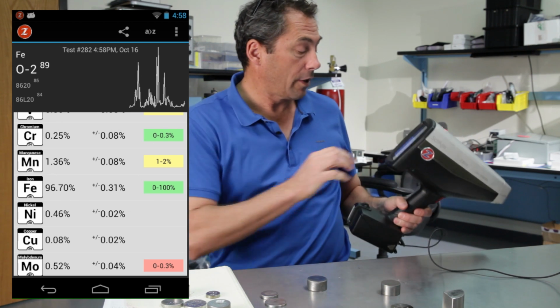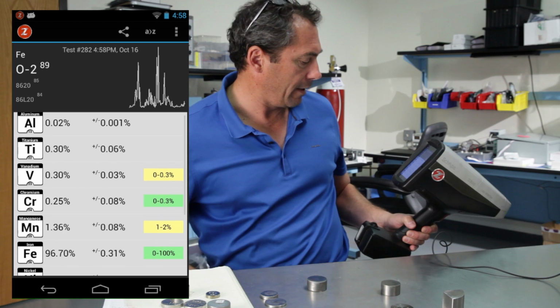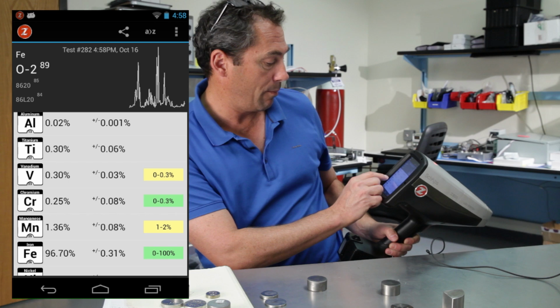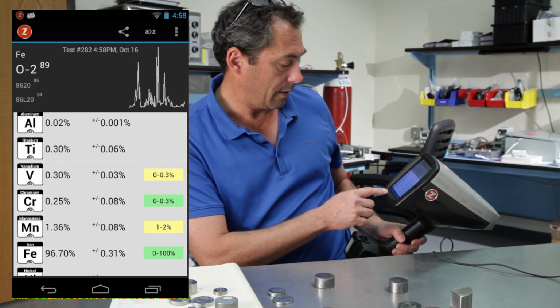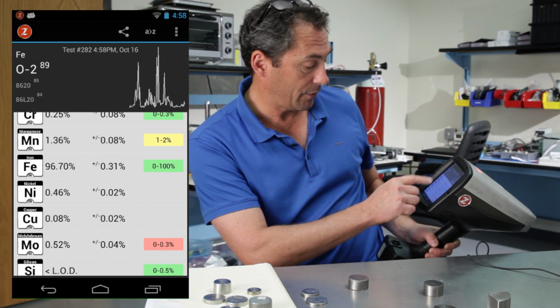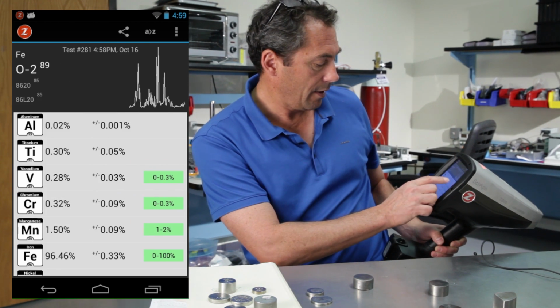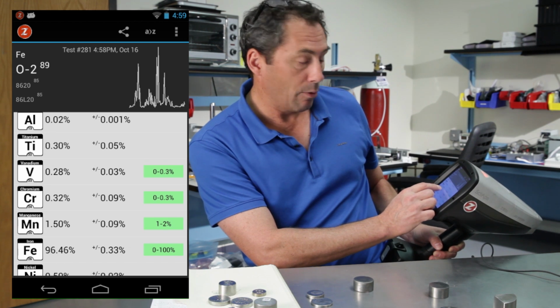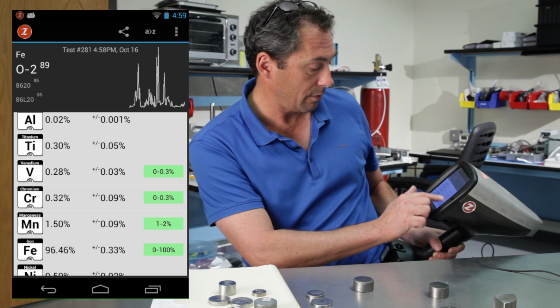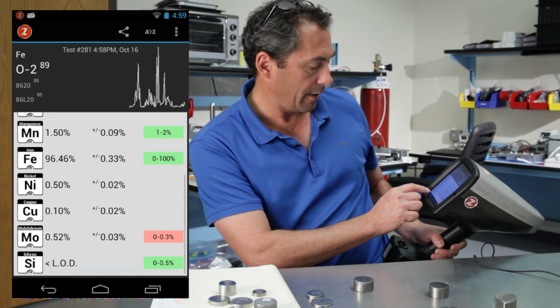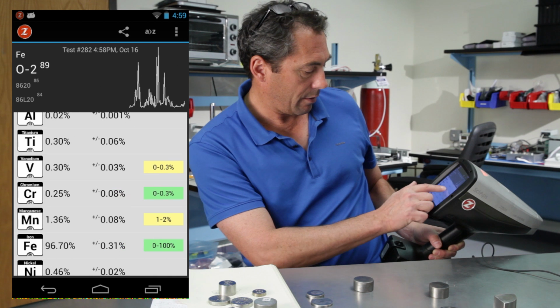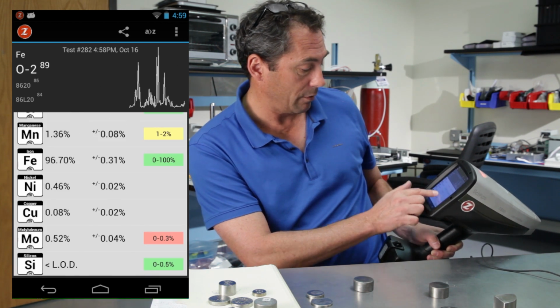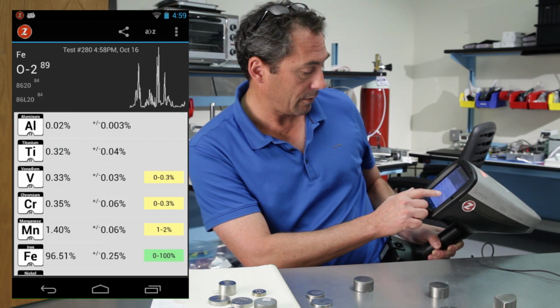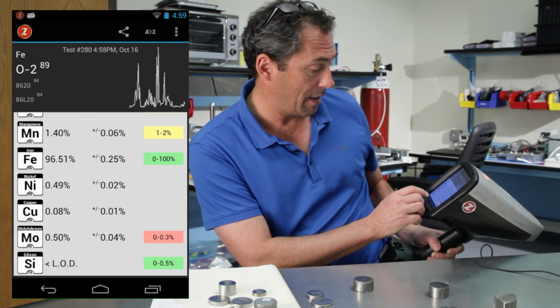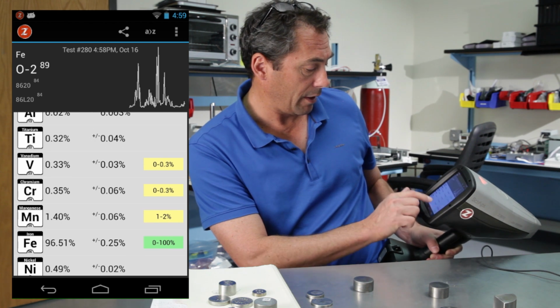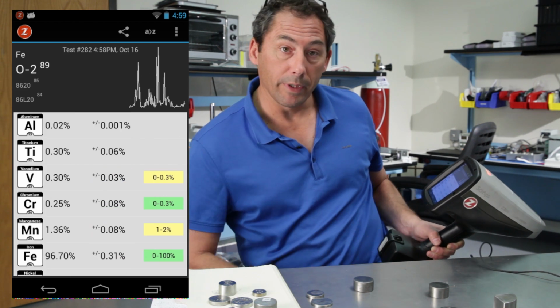And then the thing to show is looking at the chemistry of these. So I want to focus on titanium, vanadium, some chrome. So test 1, about 0.3% Ti, about 0.3 vanadium, about 0.25 chrome, nickel about 0.46, moly about 0.52. So try to remember those numbers as we swipe back to the last test. Ti again was 0.3, vanadium 0.28 instead of 0.3, so very good repeatability there. Chrome 0.32, let's go back, 0.32, 0.25. Let's look at nickel, nickel 0.5, and here 0.46, again a good repeatability, and then moly 0.52 in the first test, again 0.52 in the next test, and then that third test moly was 0.50. So it's really good repeatability on moly, and vanadium as well, 0.33, 0.28, and 0.3. So very good repeatability.